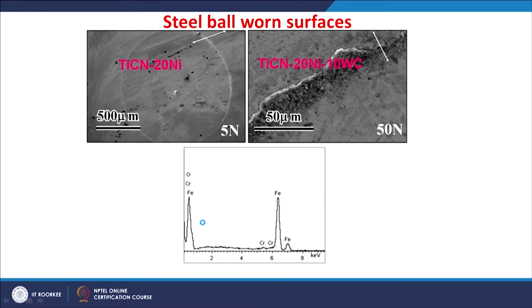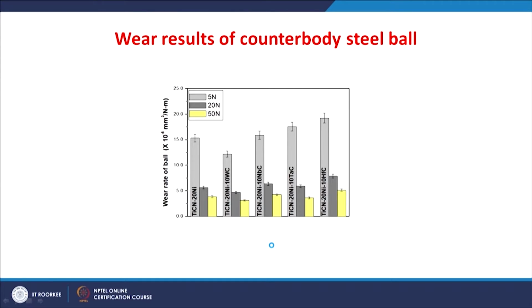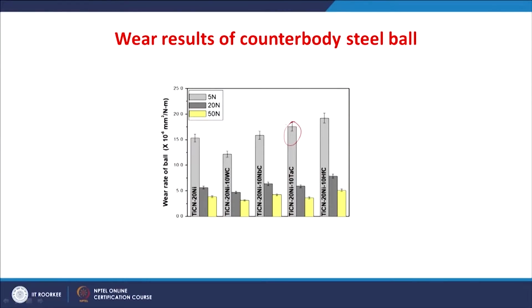The counterbody surfaces also show this tribolayer formation at higher loads. So, again these are the signatures of this layer formation, and the counterbody is also rich with the iron oxides, whereas the wear results for the counterbody steel ball show almost similar features. With increase in load there is a decrease in the wear, but a very important observation is that the cermet having the highest hardness, which showed the lowest wear at lower load, showed the highest wear for the counterbody. So, the baseline cermets actually showed lesser wear than this one.